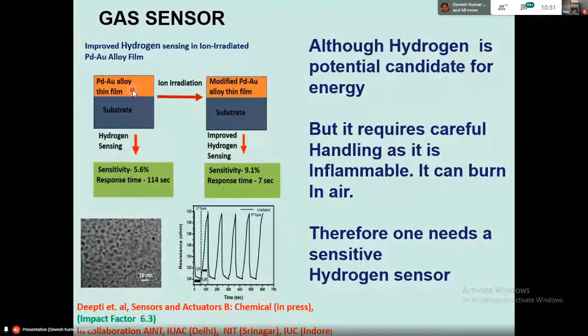This is a nanostructured film, and when we use this film for sensing, the sensitivity was 5% and the response time was 114 seconds. That means it was taking 114 seconds to give the signal that yes, hydrogen is absorbed. And this change in the resistance of this film is basically the signal for hydrogen sensing. Now, if this film is irradiated by ions, which was done, and then utilized again, the sensing is improved. It showed 9% sensitivity, and the response time was 7 seconds only, where earlier it was taking 114 seconds.